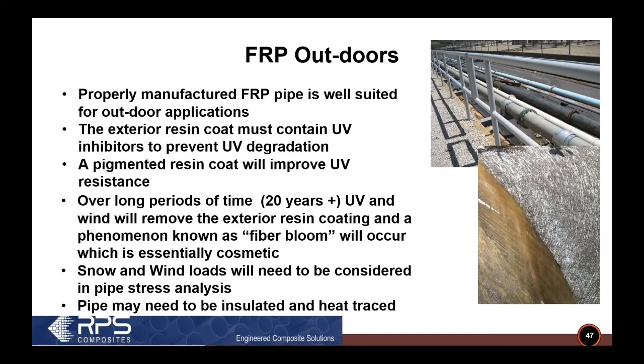When you get to outdoors, FRP pipe is used a lot outdoors as well. The pipe will be finished with a UV inhibitor, and that's really important. You can see in the picture at the bottom, that's an old piece of pipe from up in the boneyard, and on the left-hand side, the pipe has the UV inhibitor in it, and on the right-hand side was just a cutoff from the mold.